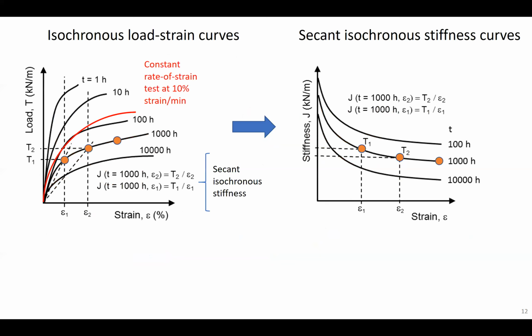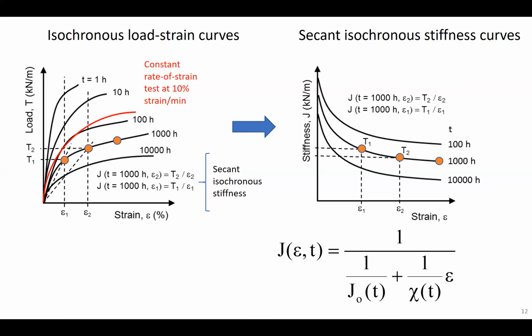So after connecting these points on an isochronous curve, we can then construct a secant isochronous stiffness curve as shown on the right-hand side. Okay, so each one of these points has a slope, and at the same strain, I can then plot that slope on that particular isochronous curve, and this gives me an isochronous stiffness curve. And a two-component model of hyperbolic form can be used to capture that trend quite nicely.